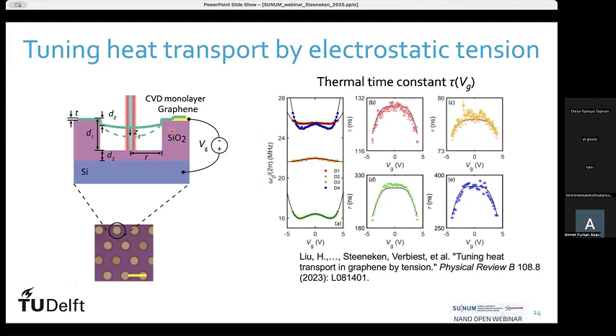Then we thought, well, if this is really so important, can we also tune the speed by which heat is transported over a graphene membrane by increasing the tension in the membrane? Thermal energy is transported by sound waves. So if we can increase the speed of sound in the material by tensioning it, we might increase the rate at which heat leaves the membrane.